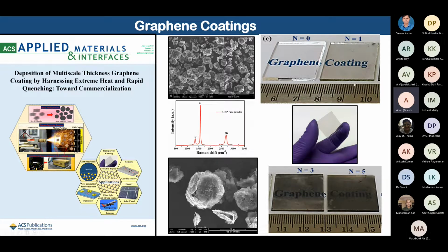On the right hand side, you can see the graphene coated over the glass substrate. N equals 0 means there is a bare substrate. N equals 1 means only one pass we have given. N equals 3 means 3 passes have been given, and N equals 5 means 5 passes have been given, 5 layers have been deposited, right? So you can see how the color is changing. Layer 1 has little transparency, which gets darker and darker as N approaches 5, right?